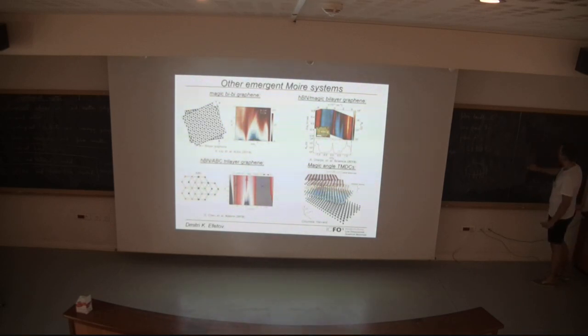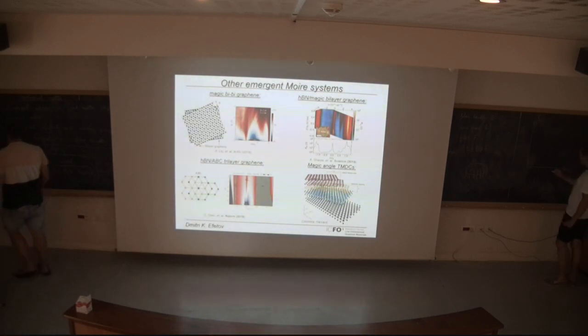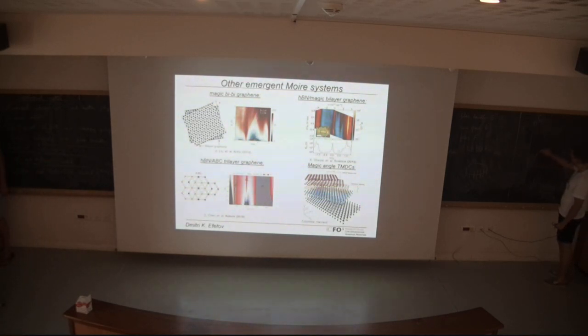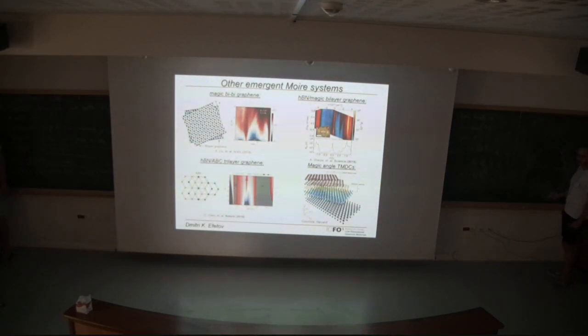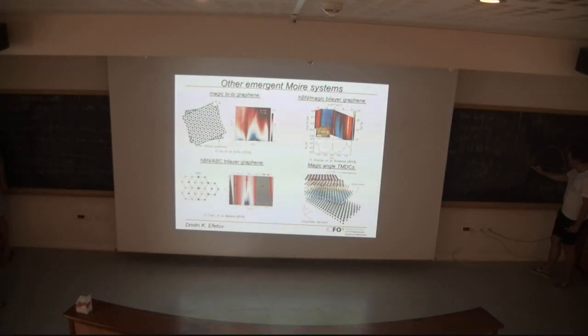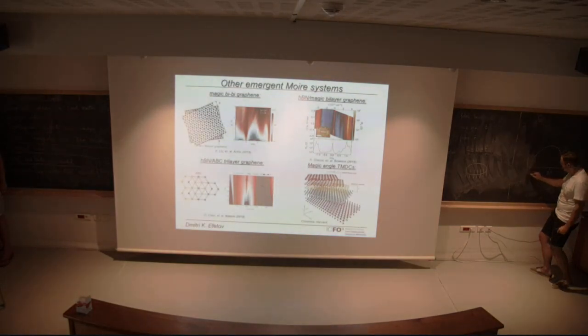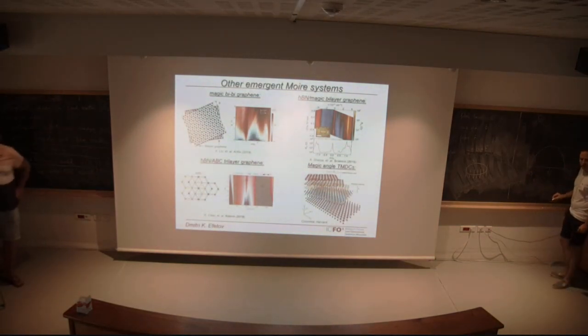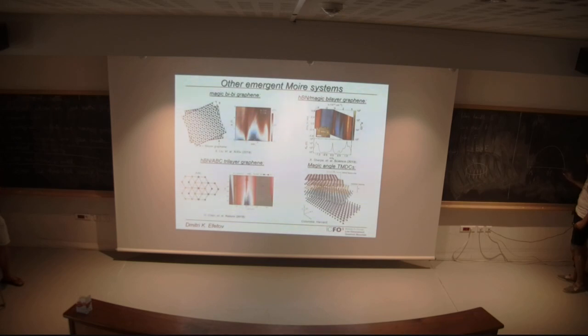So basically, if one draws TC as a function of twist angle in magic angle graphene, then you would get something like a dome shape where max TC of around 3 Kelvin is at 1.1 degrees, but you still get signatures of superconductivity at 0.9 degrees, and you still get it up to 1.2 degrees.